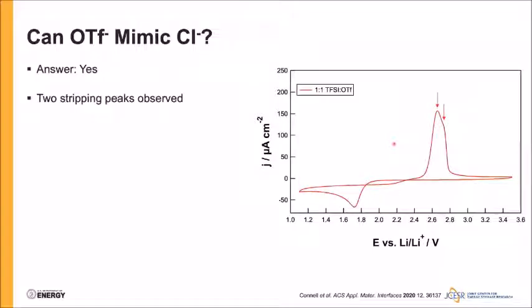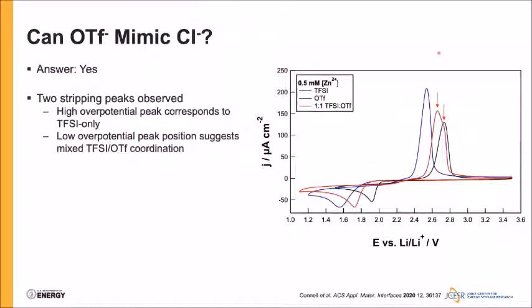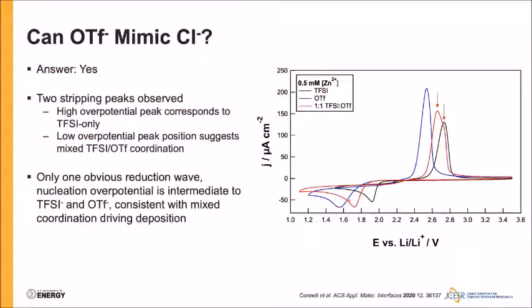In direct analogy to the mixed TFSI chloride system, we see 2 distinct oxidation features in the mixed TFSI triflate system. And if we overlay the voltammograms I just showed, we see that this first oxidation event overlaps exactly with that of the TFSI only system. But this lower overpotential peak sits directly in between the 2, the triflate only and the TFSI only, suggesting that there is mixed TFSI triflate coordination in the system, in some contrast to what appeared to be distinct populations in the TFSI chloride system. We also see only 1 obvious reduction wave, which is again consistent with mixed coordination driving deposition, and the location of this peak is again directly intermediate to the triflate only and TFSI only cases.